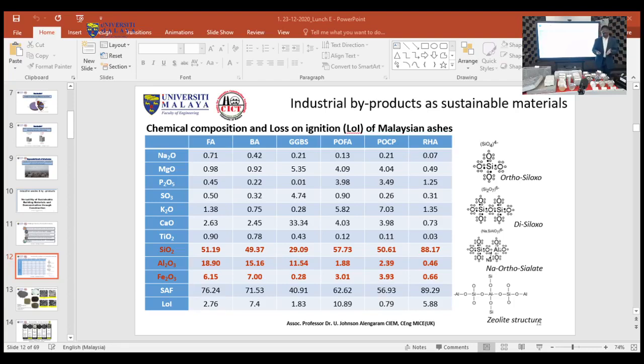So these powders that you see, they have silica, alumina, and iron oxide. These are the very important characteristics that can be emphasized for them to be used as cementitious or pozzolanic materials. So if you look at this, you can see these three aspects for each of these materials. It's quite useful for us that we can use some of these materials. Also the scanning electron microscope images show us the nature of these particles.